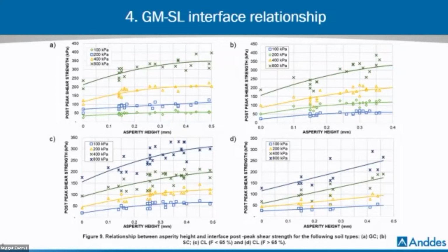Regarding the data for these correlations, most of them were obtained from shear tests between soil liner and LLDPE single-side textured geomembranes. But as mentioned, the thickness of the geomembrane has not been considered. The maximum normal stress was 800 kilopascals. And in this case, we didn't consider silty soils because we don't have enough information, and the correlation was low.